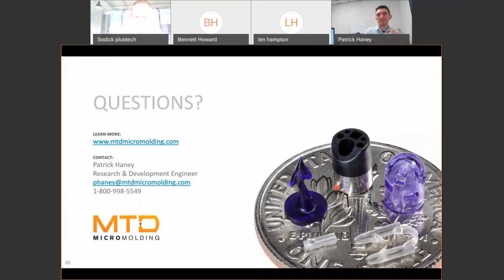Cool. Yeah, so residence time, like a lot of things when it comes to micromolding, is something that you have to take sometimes with a grain of salt, because what is practical might not be possible. So when it comes to residence time, if you're expecting to have a high residence time, there's a few things that you can do to help prevent any excessive degradation. One of those things is a higher throughput, of course. Another thing that we see is that we have high residence times, but we have small barrel capacities. So sometimes if we just have a small amount of resin that has been cooking for a certain amount of time, it's not surrounded by a massive amount of heat. Things like that will help us to prevent degradation due to residence time.